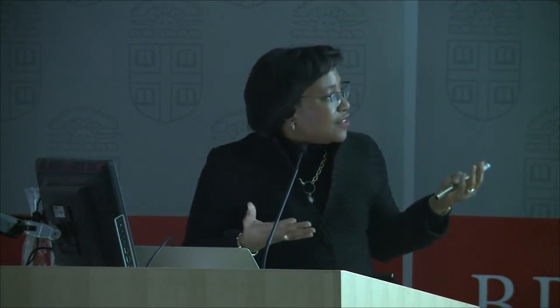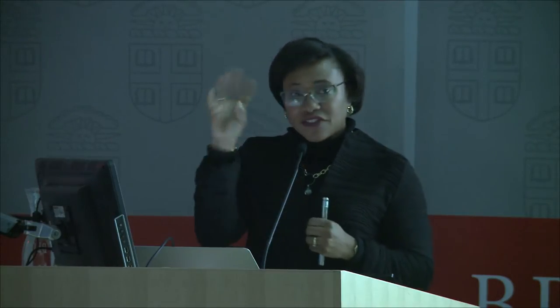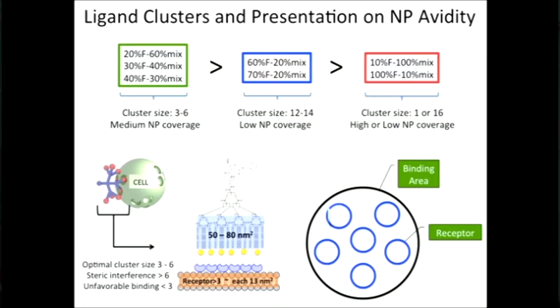So we tried to think about this in a physical way. Why would this trimer of folate, when it's clustered together, work better than any of the other systems? And what we did was essentially explore how big of an umbrella this dendrimer makes in or around the cell membrane surface. And what we see is that we can sort of map out that region. If we know how big the receptor is, we can also map out how many receptors fit in that umbrella or cone over which this dendron should be represented on the surface. And we figure that about 6 binding opportunities are available from this dendron.